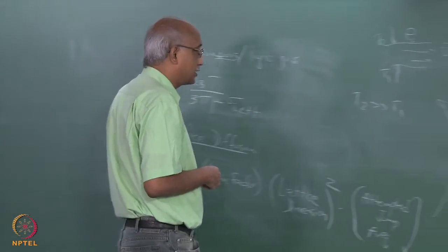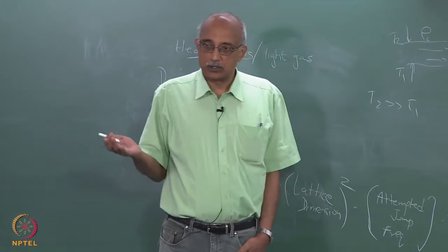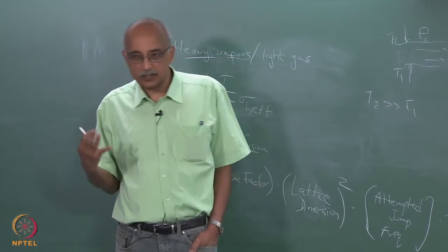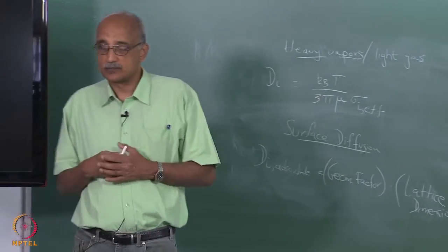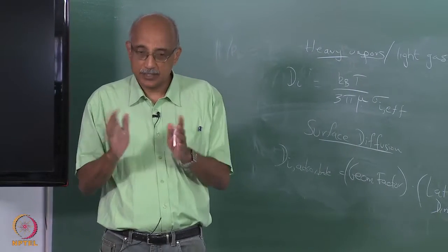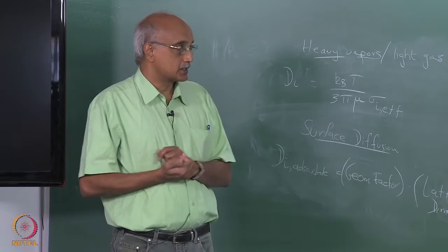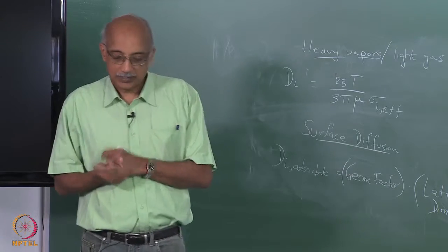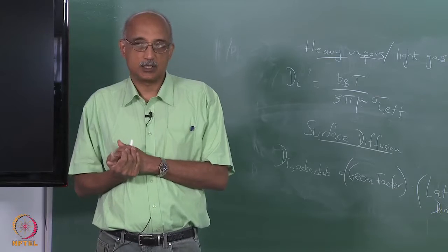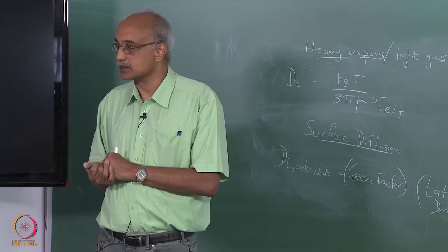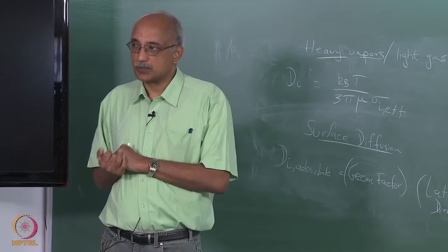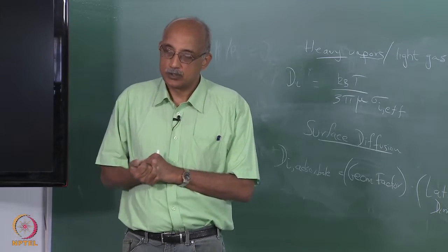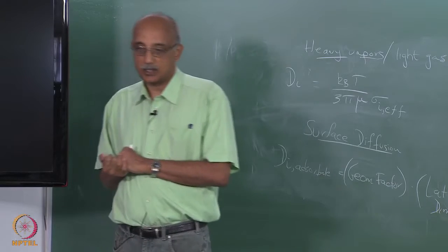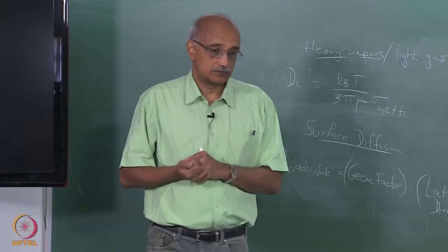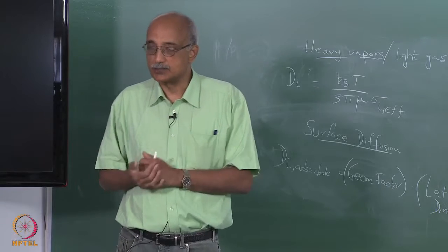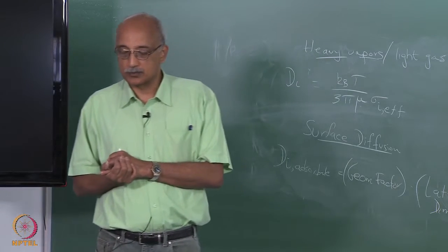Another field that you can think of is just gravity. In all our discussions of CVD, we have kind of neglected gravitational force, but it is present and it can have an effect. So, the gravitational field itself induces a phoretic effect. For example, in a CVD reactor, what would be some of the dominant phoretic fields? Certainly thermal, because particularly in a cold wall reactor, you know that the temperature gradient between the substrate and the walls of the reactor can be in the range of hundreds of degrees. So, the thermal gradient we do need to account for.